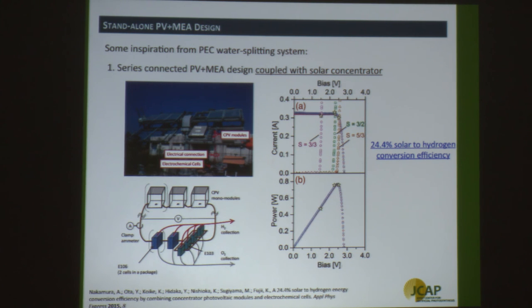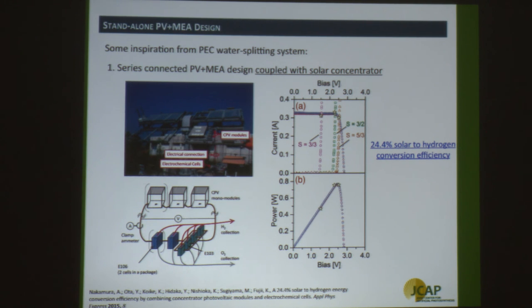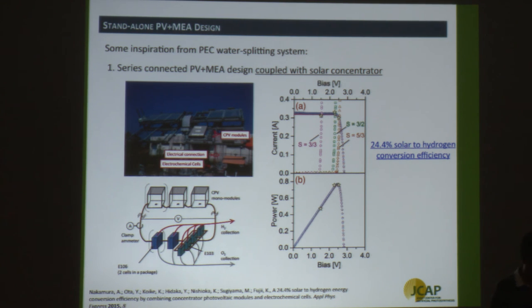State-of-art demonstrations include three perovskite cells connected in series providing enough voltage for CO2-to-CO reduction using iridium oxide for OER and structured gold catalyst for CO2R — achieving 6.5% solar-to-fuel conversion efficiency, the highest reported PEC CO2R efficiency. Another demonstration using series and parallel connected CIGS modules with a fuel-cell-type membrane assembly reached 4.5% efficiency. Inspiration also comes from PEC water splitting: a Japanese group demonstrated above 20% solar-to-hydrogen efficiency using high-efficiency PV with a solar concentrator.